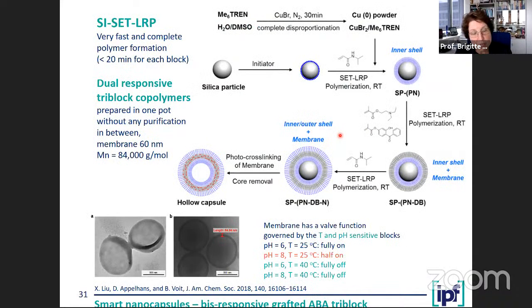Okay, a couple more chemistry, because I wanted to show you also the techniques which have been developed in the last years for making very much controlled synthesis. You see here a variation of the ATRP. It's a so-called SET-LRP. It's again a living radical polymerization. It allows you, and we developed a very nice scheme, to also make block copolymers. And we made a nice development here that we got really very thick membranes by that grafting process of a terpolymer, for example. And that is also nicely controllable.